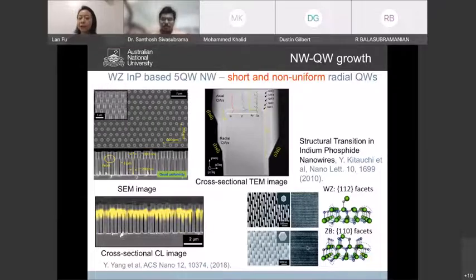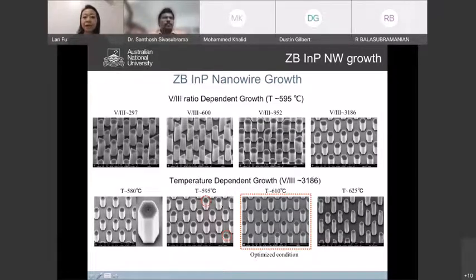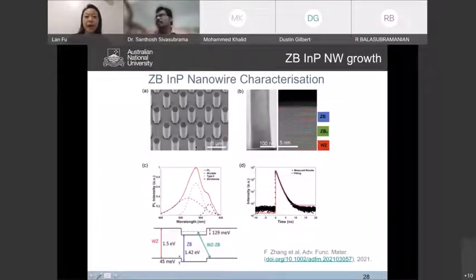So we were thinking that if we can create a zinc blende base of indium phosphide, we can probably create more uniform indium gallium arsenide quantum wells from there. My students did a lot of optimization by changing the growth temperature, growth rate, V/III ratio, and all this. We were able to find a good condition to grow this optimized zinc blende based indium phosphide. You can see it has a very nice morphology. And we did some TEM analysis and also optical analysis, really showing that this zinc blende based indium phosphide also has very nice optical properties.